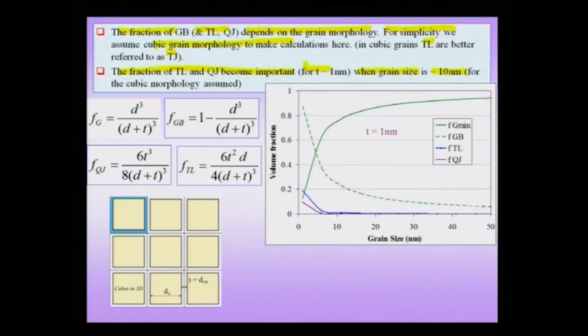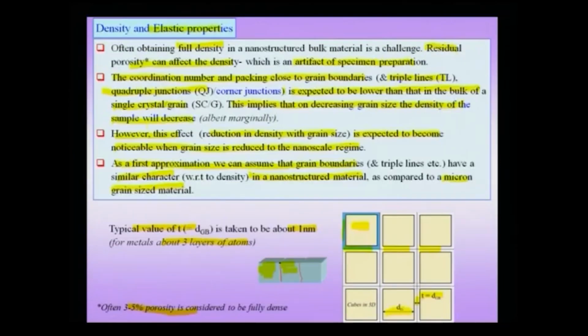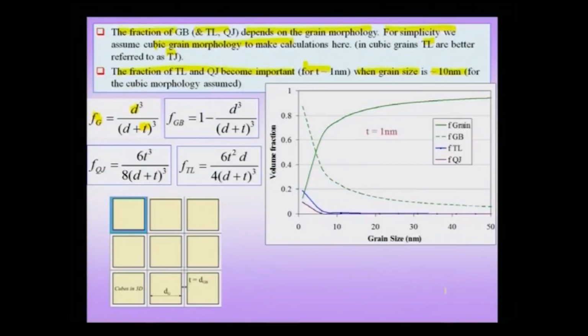The fraction of grains as a function of the size of the grain, which we have shown here as d, and the size of the grain boundary, which is T, can be written as d cube divided by (d plus T) the whole cube. This is a pure geometrical calculation based on the cube morphology. The fraction of the grain boundary region can be written as 1 minus this value. The fraction of quadruple junctions can be given as 6 T cube divided by 8 into (d plus T) the whole cube. The fraction of triple lines can be given as 6 T square d divided by 4 into (d plus T) the whole cube.